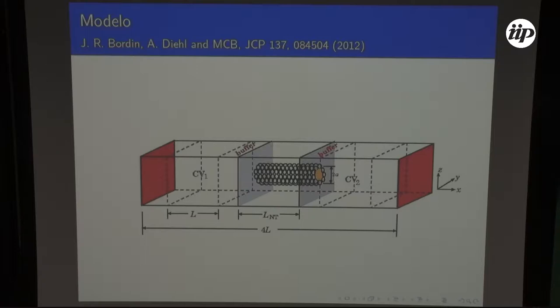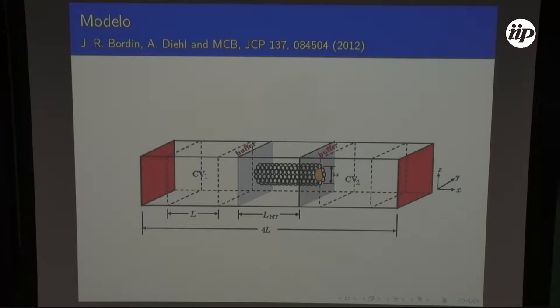What people did is confine water in carbon nanotubes — here is just a cartoon for the simulation, where you put water inside the carbon nanotube. Many interesting things happen. One thing I'm not exploring here is that when you have flow, the flow of water in carbon nanotubes is a thousand times faster than it should be according to hydrodynamic equations. This is related to the fact that water lines up through a single chain of hydrogen bonds when it's in a very tiny tube — hydrogen bonds play a very important role. If you put another material in carbon nanotubes, you don't get this enhancement of flow.